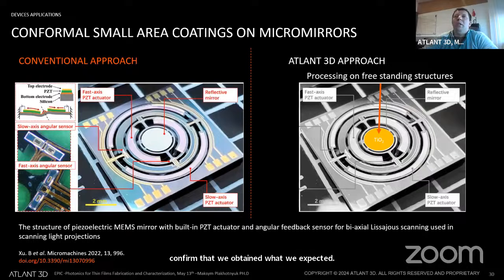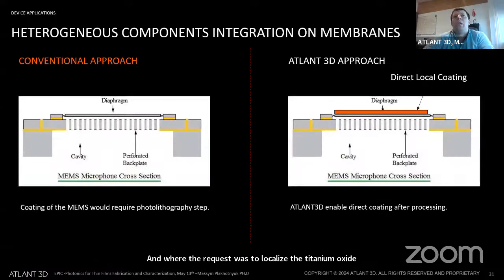Another development that we did recently with Silicon Austria Lab is local deposition on micromirrors, where the request was to localize the titanium oxide in this area. It was successfully accomplished. So working on very sensitive diaphragms or any other very sensitive elements is also quite easy for us. We pre-program the area that we need to deposit, and then the printhead goes to that area and does the deposition.